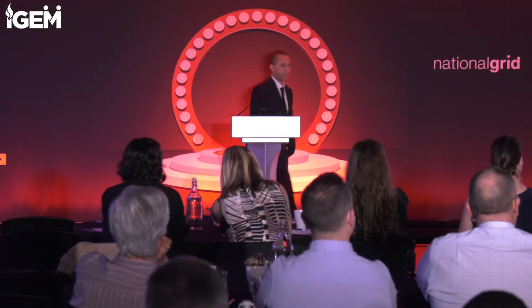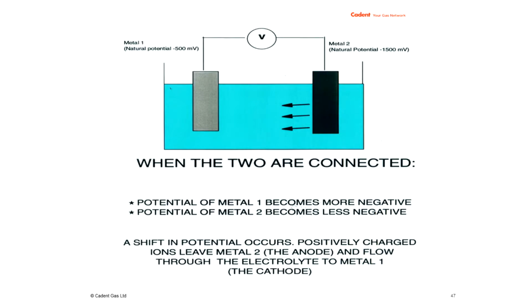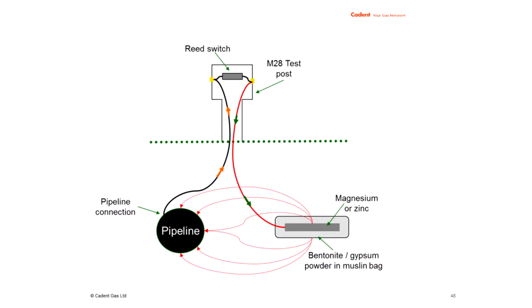So when you connect the two together, this is what happens. Metal 2 on the right-hand side will become less negative, so that is in effect our anodes. And metal 1 on the left-hand side, which is our steel pipelines, starting off at minus 500 millivolts, will become more negative. And so that's the reaction that occurs. And basically, when that reaction occurs, we will soon be able to tell if our pipelines are protected by the change in potentials. This is a cross-section of how the connection is made.